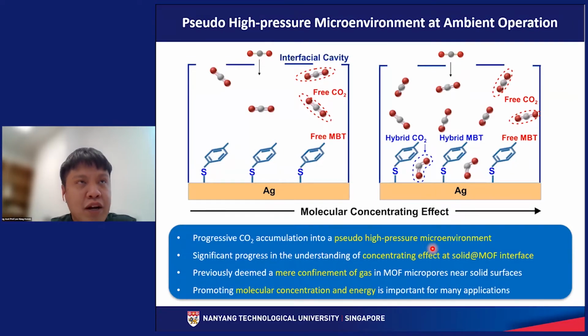So this is a very significant progress in the understanding of concentrating effect at solid MOF interface. So usually in the scientific community, it was deemed that the gas concentrating effect is merely a confinement of gas molecule in the MOF micropore very near to the solid surface. So this is not entirely true, but over in this work, we are trying to say that we are able to continuously accumulate carbon dioxide molecule into a pseudo high pressure microenvironment. So achieving this is important because we want to promote molecular concentration and energy, because this is the basis to drive chemical reaction.